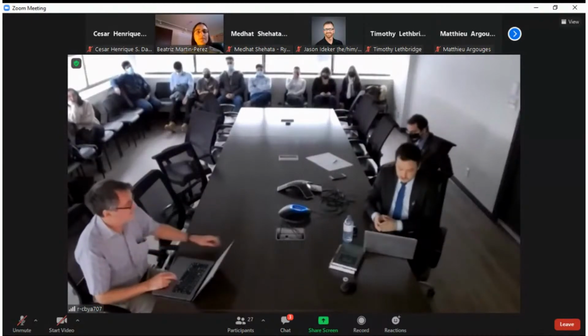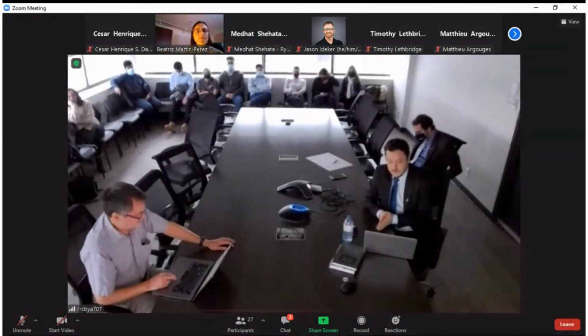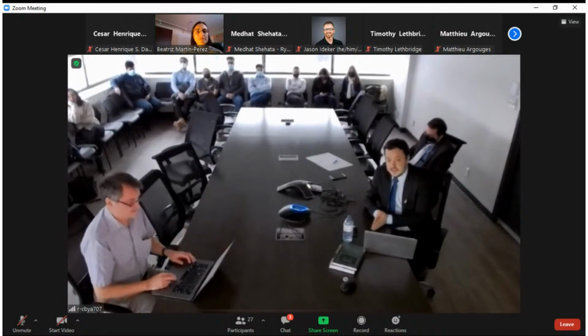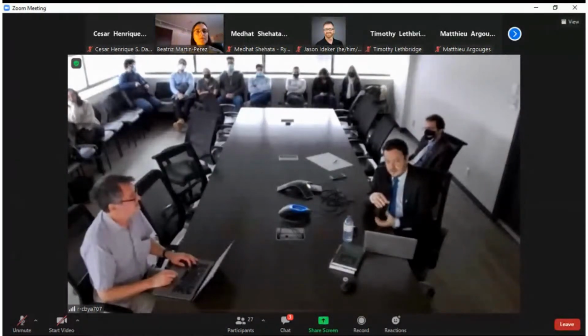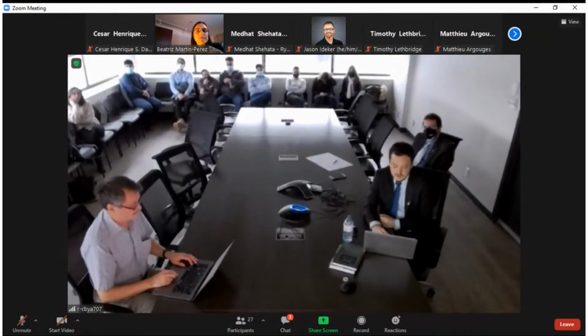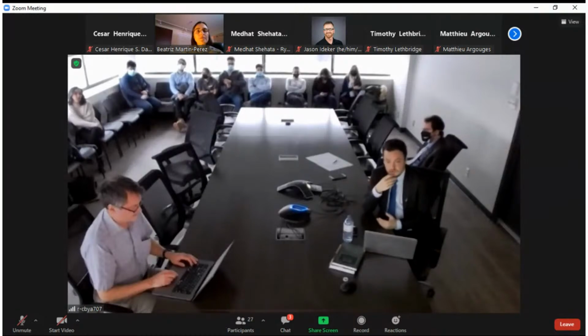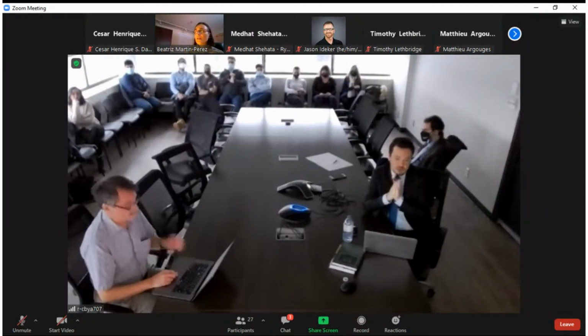Yeah. Here, first, it's not exactly at 0. We preload the specimens, for example, at 28 days, and then we test for compressive strength, for all tests that we made, 3 days after the preloading, because we would like to have some recovery of the concrete after the preloading. And this variation here is calculated based on the specimens that we did not apply any preloading level on. So it's basically the difference between those that we test without preloading and those with preloading levels.